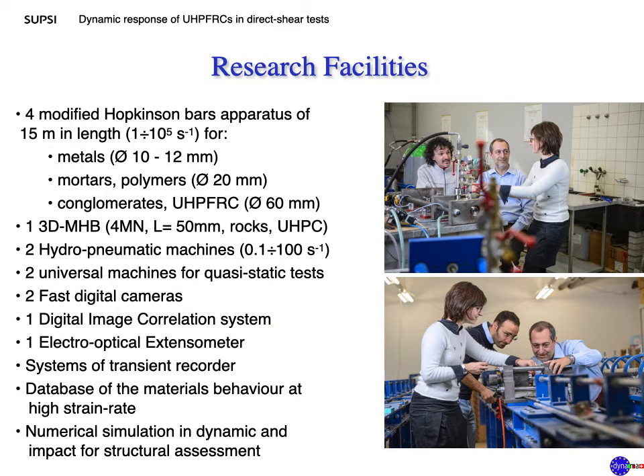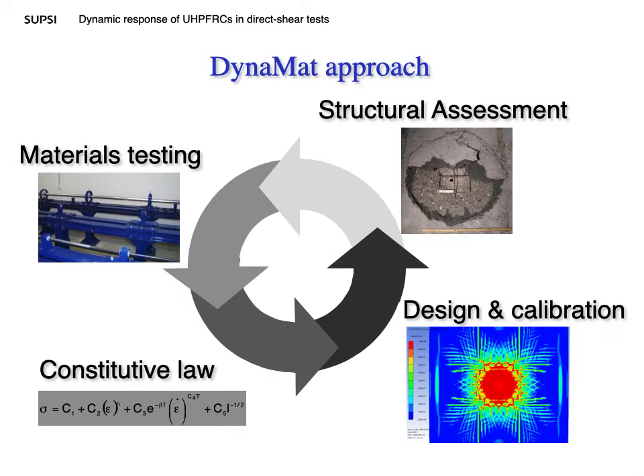This laboratory is equipped with several modified Hopkinson bars for testing metals, polymer, concrete, rocks at a high strain rate. We have also 2 hydropneumatic machines for medium strain rate and 2 universal machines for quasi-static. With this philosophy, starting from the material testing, we calibrate existing constitutive law or create new ones. The third step is the design calibration in the finite element code, and finally the structural assessment is performed with the partner. The aim of the